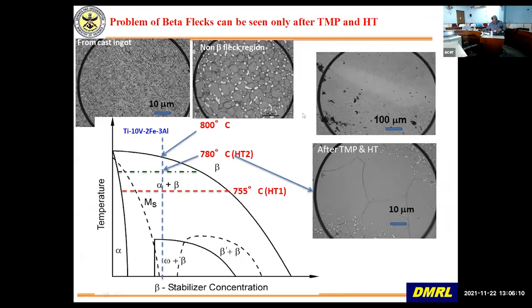Here again, I'm showing you the microstructure. Here, no beta fleck, but whenever you have a beta fleck, after thermomechanical processing, you can see these retained beta regions. You can see here. So you have big beta grains as compared to the other regions. So what happens is fatigue cracks normally start initiating there because of the strength differential, and you have a problem.